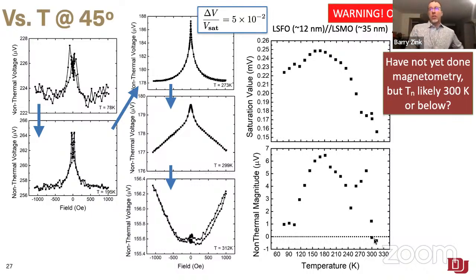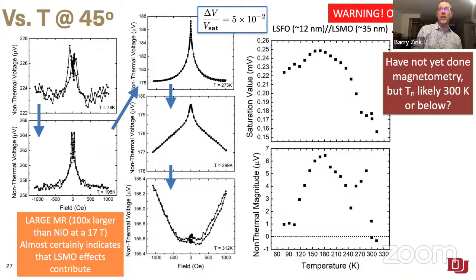Now, we haven't done magnetometry on this exact sample, but I can show you some in just a second on a companion sample, a similar material where the Néel temperature in the LSFO is near 300 Kelvin. The Curie temperature of the LSMO is right about 350 Kelvin. So this could be a sign of interesting things happening generated by the antiferromagnet, and maybe not such interesting things happening in the ferromagnet.